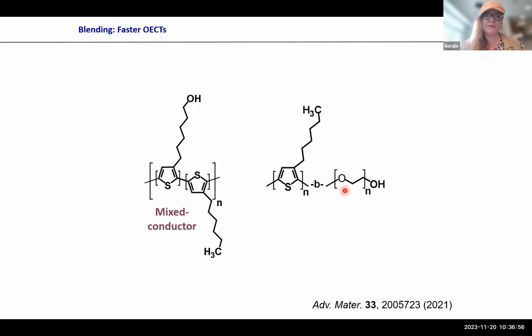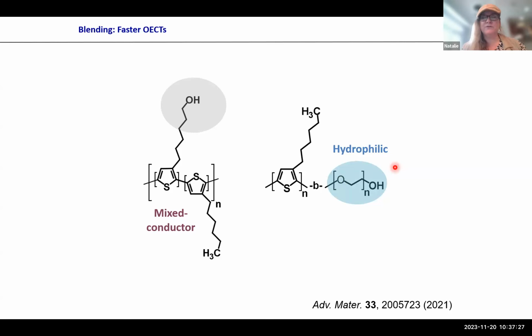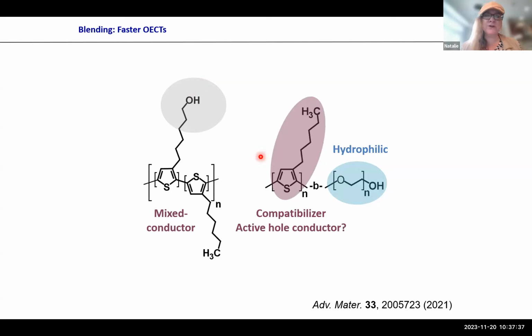So why did we pick this one? While the P3HHT is somewhat polar, we really worried about compatibility if we add, let's say, polyethylene oxide. With P3HT, we still could find co-solvents, but once you have stark differences, let's say, of your semiconductor and your polar material, the commodity polymer like polyvinyl alcohol or polyethylene oxide, you start to have problems. So we used some hydrophilic groups to make this monomer unit happy of the P3HHT, but also added a P3HT block to make the other unit here in P3HHT happy in this sense.